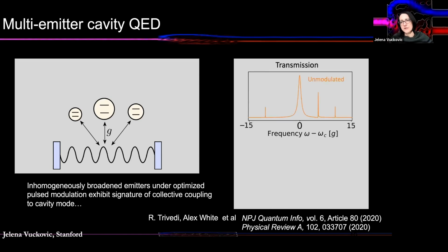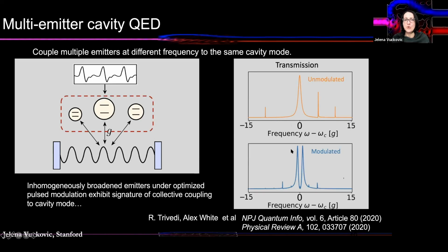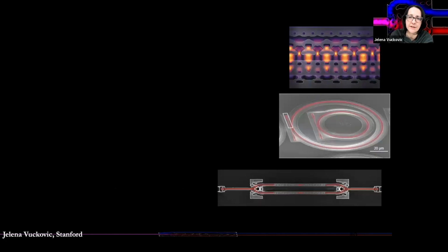So you put a single set of electrodes on these inhomogeneous emitters, you know where their transition frequencies are. Can you recover superradiant behavior and collective coupling to a cavity? If they're just inhomogeneously broadened, you measure transmission, there is nothing interesting going on. There is a cavity resonance and 3 transitions for emitters. But if you modulate all of them with the optimized drive that we found, then you can recover this strong coupling. And that is very exciting for us, again, because that means that with a simple configuration, you can scale systems up to larger number of qubits working together.